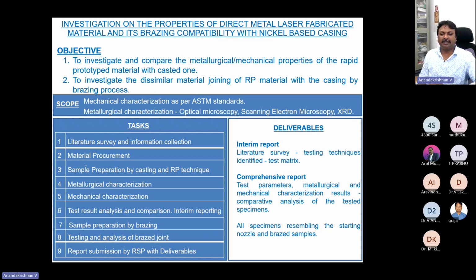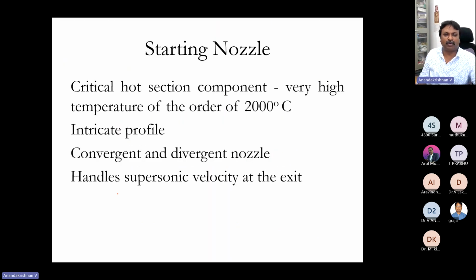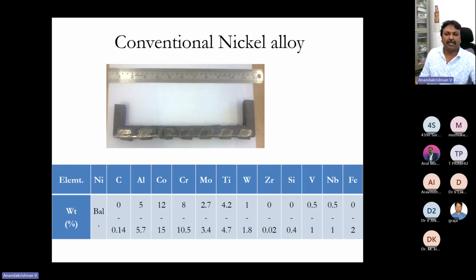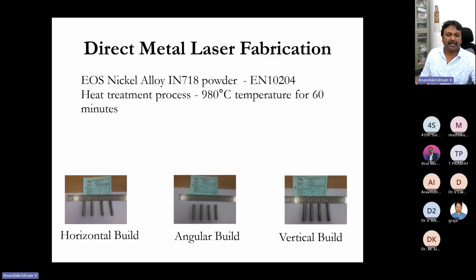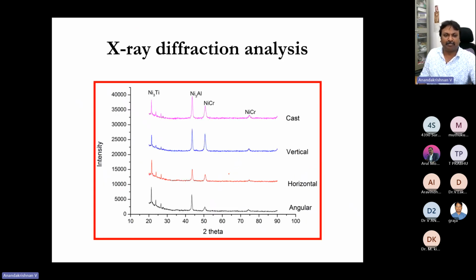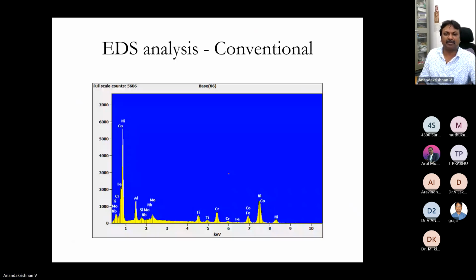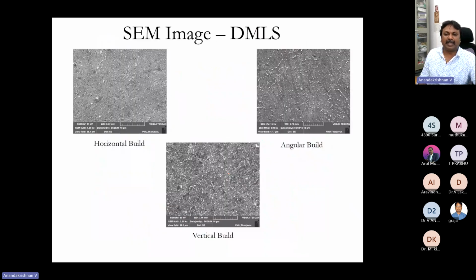And the production department in Trichy, along with myself as a PI, we have taken up something like, as I told you, the starting nozzle in that engine, right? That starting nozzle has to withstand around 2000 degrees centigrade in a convergent divergent nozzle. And we did some analysis, right? By printing the component in the horizontal axis, angular axis, and vertical axis, and then we did X-ray diffraction analysis, scanning electron microscopy analysis, energy spectroscopy, and then elemental analysis.